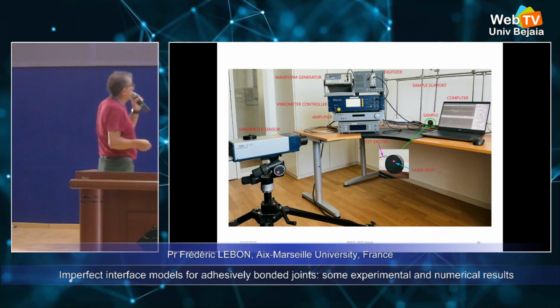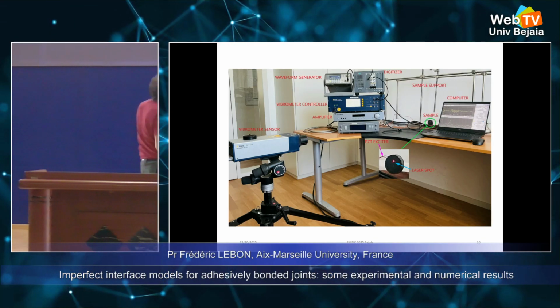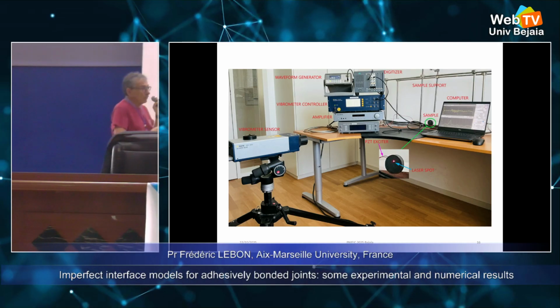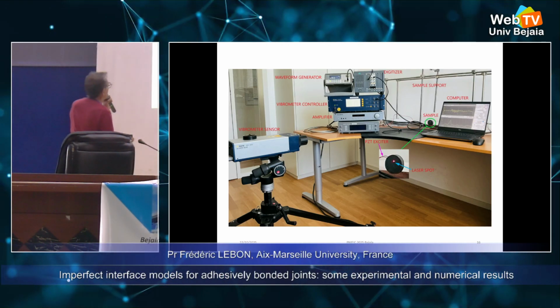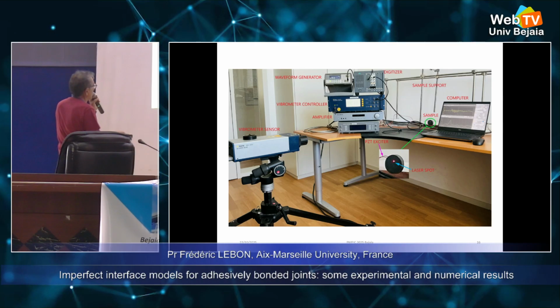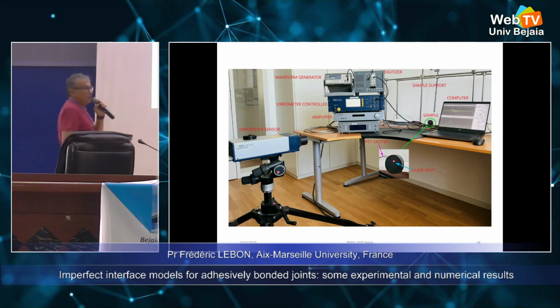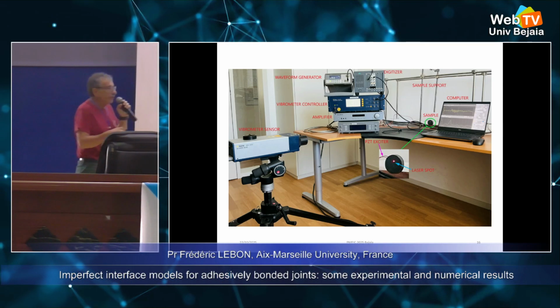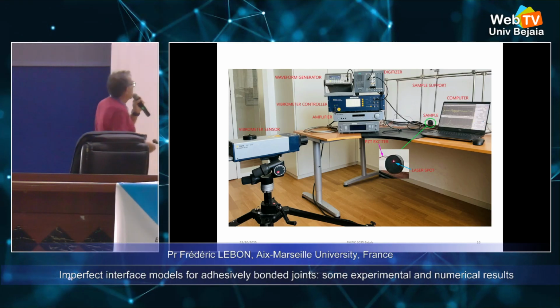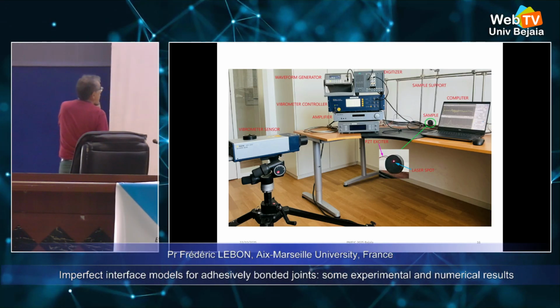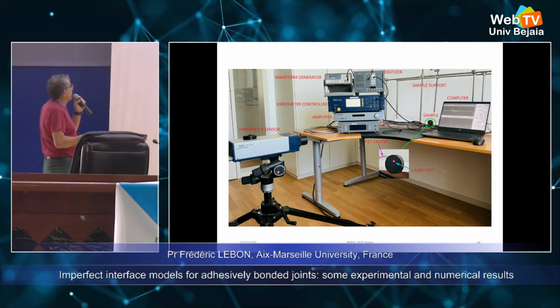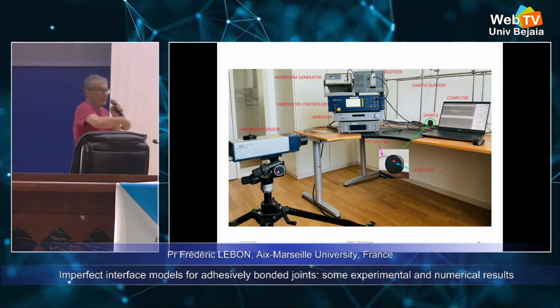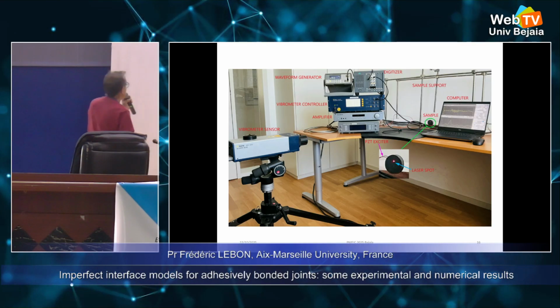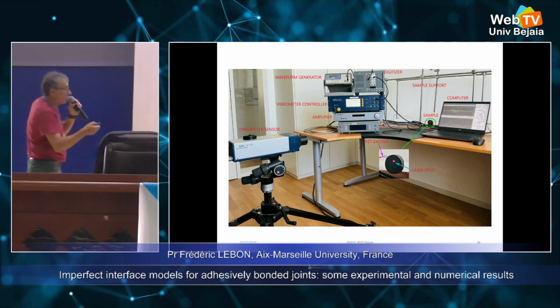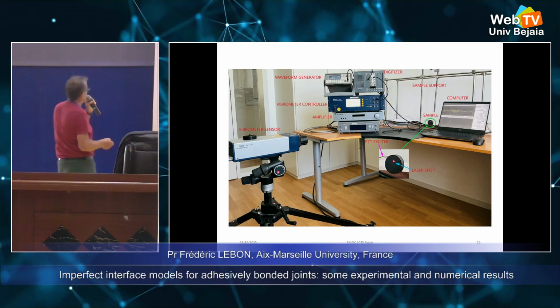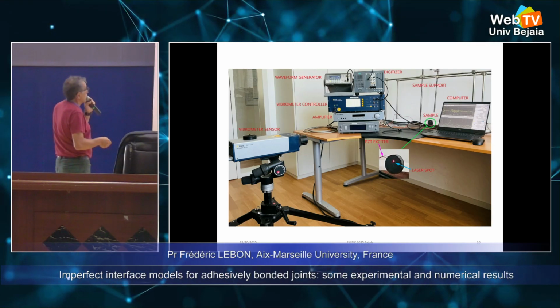It's an experiment in vibration, because we are in a laboratory of acoustics. We excite the sample here, which is a disk, and we can observe using Fourier transform the resonance modes, and we can compute these resonance modes using finite elements. We can compare, and we can deduce the rigidity, the Poisson ratio, and so on. And so we can do that.